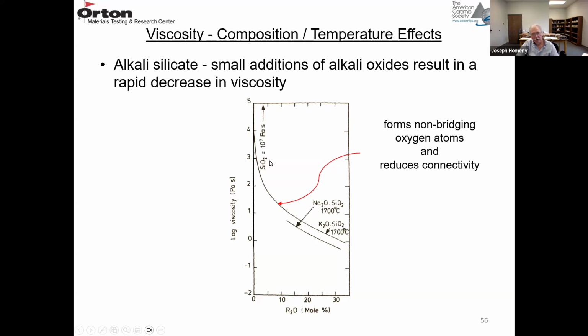So as you add Na2O, the top curve, and K2O, the bottom curve, you can see the drastic decrease in viscosity. So as you're adding Na2O or K2O, you're forming these non-bridging oxygen atoms. You're reducing the network connectivity, and you're really decreasing the viscosity. So if you have a silicate glass in a refractory and there's a lot of sodium and potassium present, it's going to be very fluid.